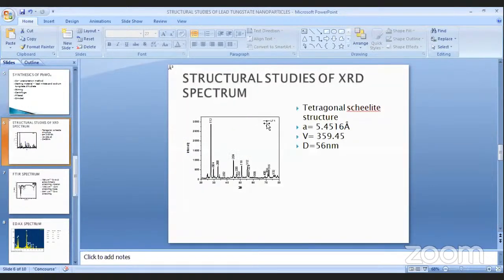Structure studies of the XRD spectrum. The XRD spectrum shows a tetragonal scheelite-type structure. In the XRD pattern, the diffraction peaks 112 and 204 are much stronger than other peaks. The lattice parameter a equals 5.4516 and the volume is 359.45. The average particle size is 56 nanometers.